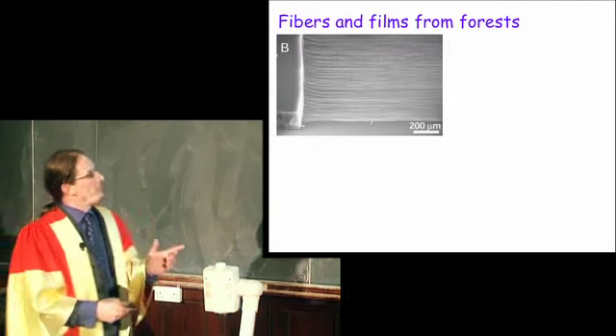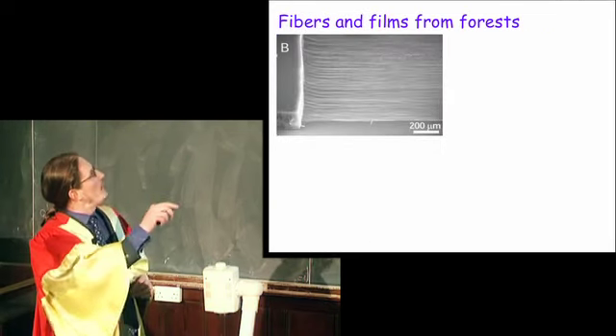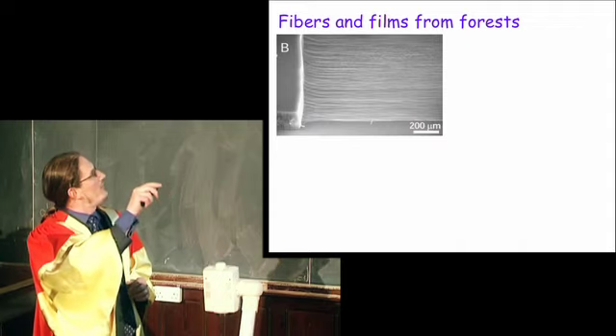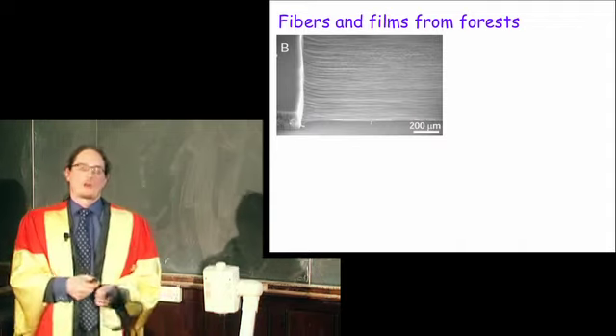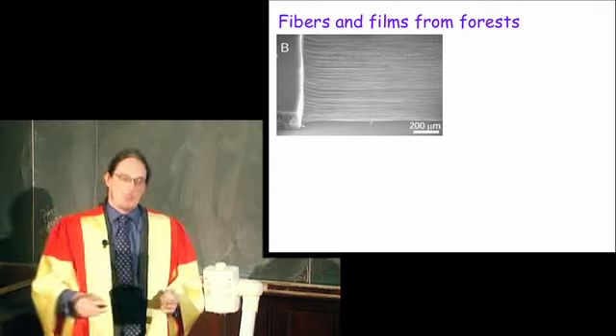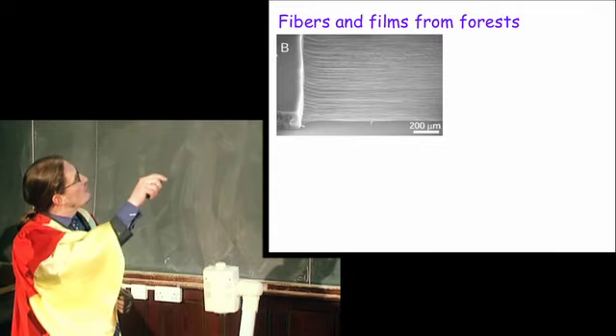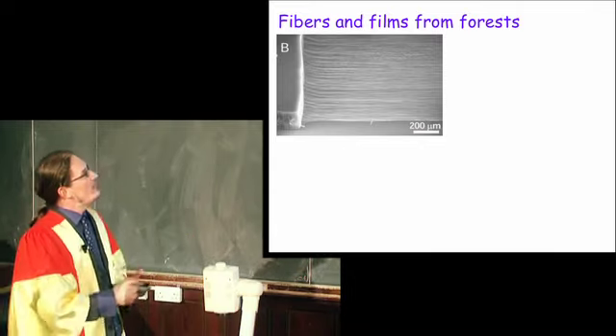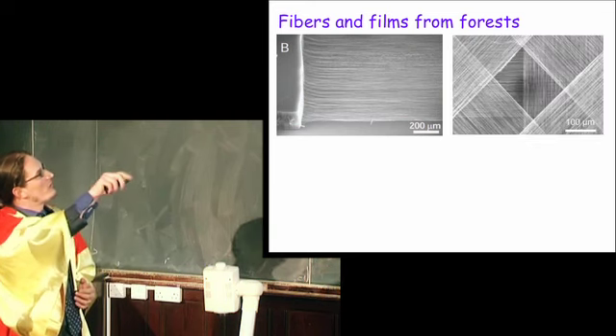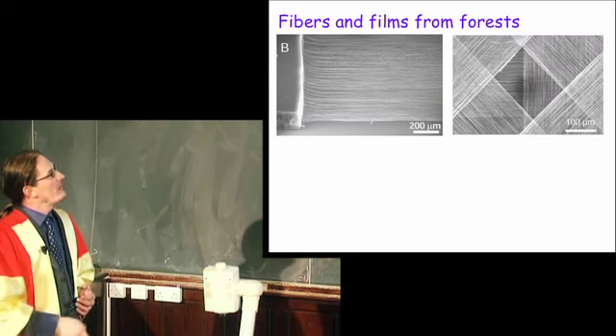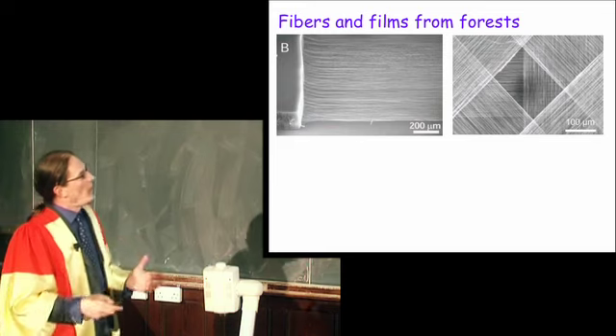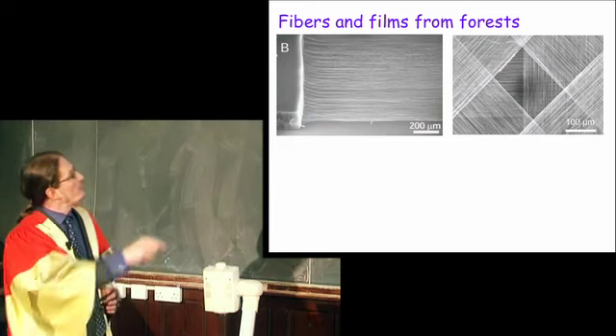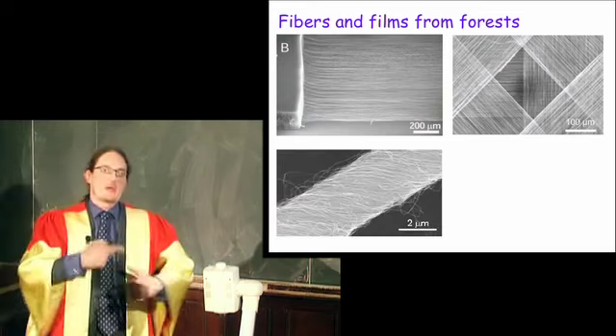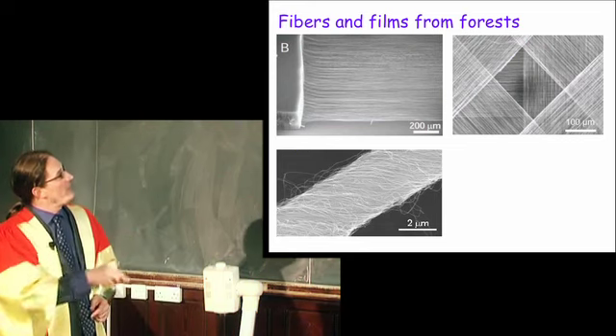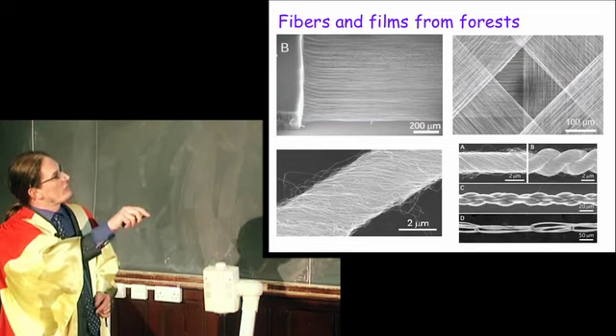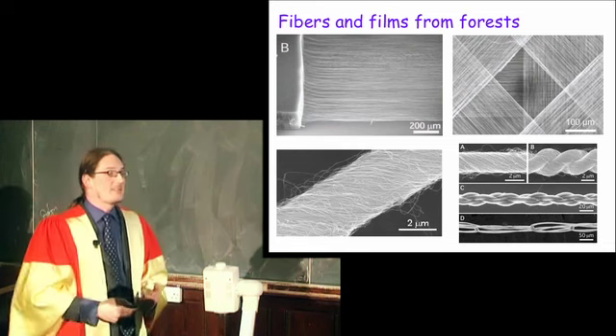So when you have the forest, as I showed you before, what people realized quite early was that if you just simply grab the corner of that forest with a tweezer and pull, you can actually pull out sheets of nanotubes. And these sheets can be laid on top of each other to form overlapping arrays that have quite interesting properties. Alternatively, such a sheet can be twisted into a fiber. And these fibers are really, really strong. They're so strong that they can be knitted or knotted.